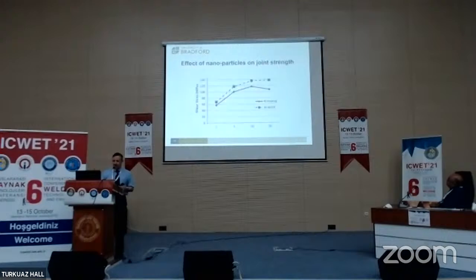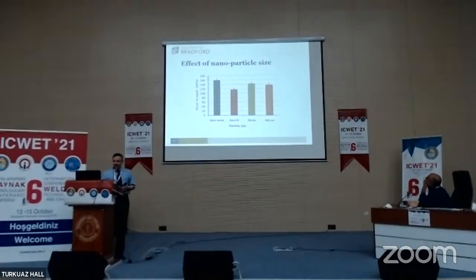And this is a better comparison for pure copper. You can repeat it for copper or nickel. We did it both for copper, alumina reinforcements as well. So for just pure nickel, we got a value, pure nickel here, and for our nickel alumina dispersed coatings, we get better strength. The particle size also is important. Obviously, here, this color histogram shows you what happens with pure nickel, but with 50 nanometer, the finer the particles, the strength is a bit better. If you use 500 nanometers, the strength is a little bit less.